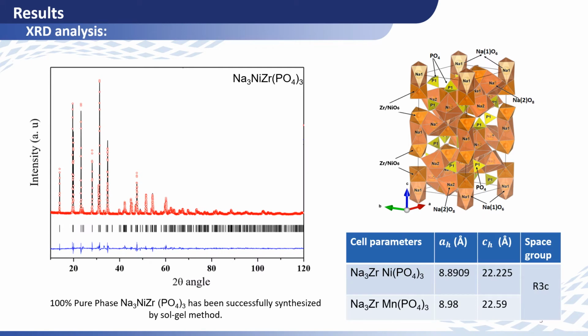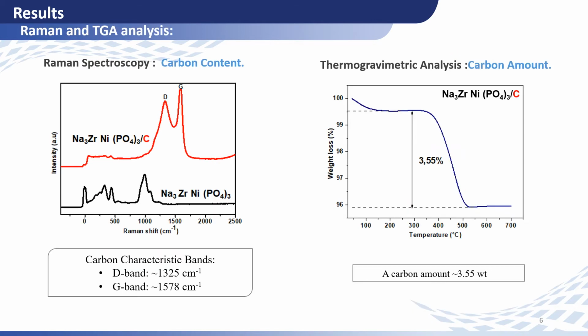For the structural characterization, the XRD analysis shows a well-crystallized sample with hexagonal symmetry and R-3c space group with the following cell parameters. The comparison with those of related compounds confirmed the accuracy of our refinement and the stability of the material. Raman spectroscopy analysis was conducted to check the carbon coating process.